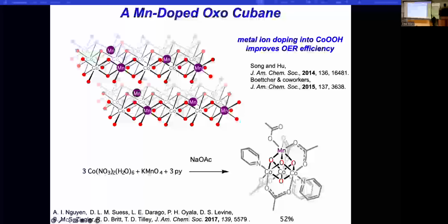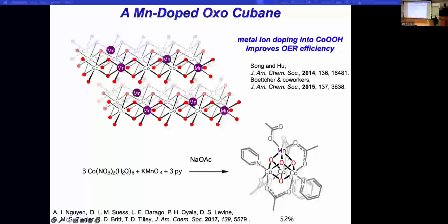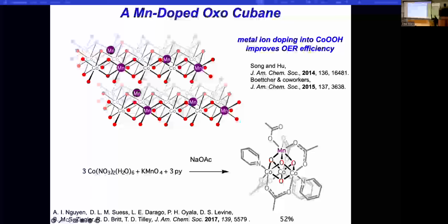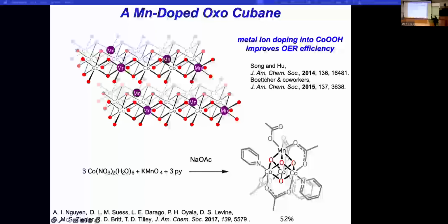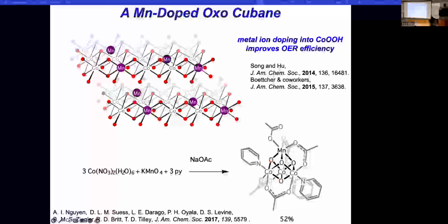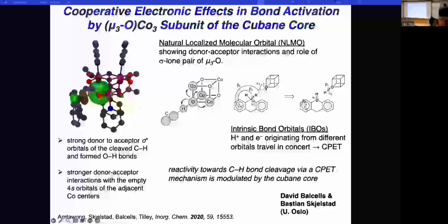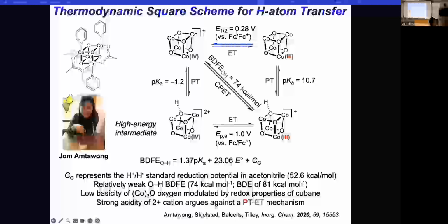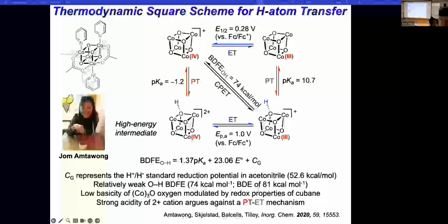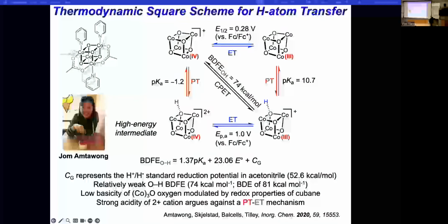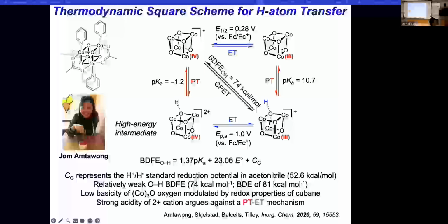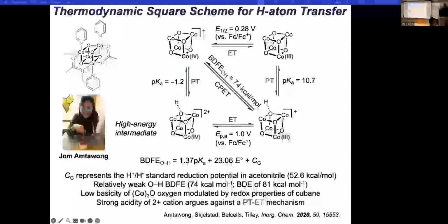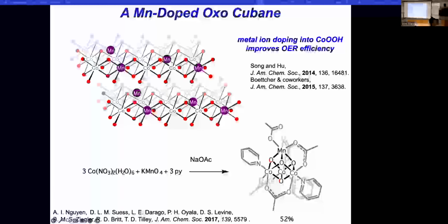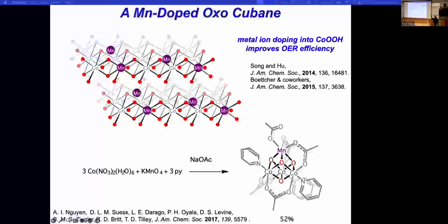Okay, I mentioned the problem with tuning the redox potentials in the context of the model for the OEC. And so cobalt is not manganese in that sense, and also in terms of this chemistry. So if we want to raise the energy of that bond, there are several ways we can go about doing that. One is to install hydrogen bonds in the rest of the cube, and we're looking at that to some extent. That brings up its own problems. But the easy solution would seem to be change the metals in the cube.